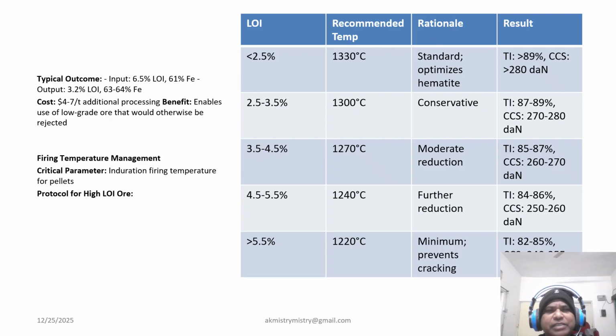Now, coming to the tumbler index measure and its dependency on pellet strength, the trend shows that where LOI is less than 2.5%, TI is between 90 to 92%, which is excellent, and where LOI is more than 5.5%, TI dropped to 80 to 84%, which is pretty poor. To counter this, we need to adjust the firing temperature: for LOI 2.5%, firing at 1330 degrees centigrade. And if LOI shoots up to 5.5%, then we must reduce the firing temperature by almost 100 degrees centigrade. These strategies help in preventing cracks and improving the cold crushing strength, which is a huge gain.